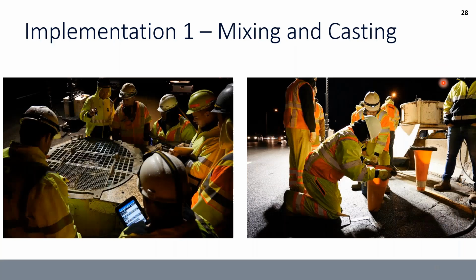With mixing and casting, this was all completed on the top of the deck. And we had 2 of these mixers going at once. We did have the partial lane closures. The core holes through the deck were done in advance. So that was something that went really smoothly. And the UHPC was actually filled all the way to the top of the deck, and so no further deck repairs were required after casting.